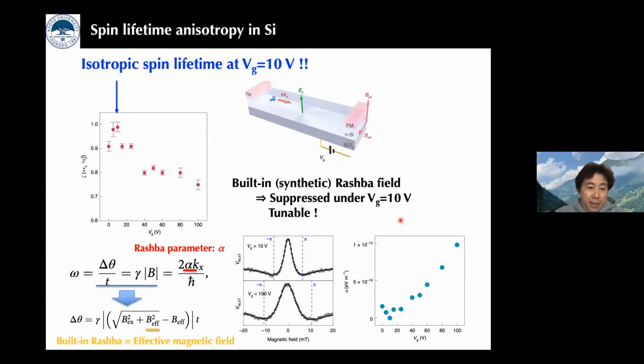This is the whole data set of the anisotropy factor as a function of gate voltage. As you see, the anisotropy factor becomes far from 1 under strong gate voltages, and the factor is also gate tunable. The other important issue is that spin lifetime is almost isotropic at a gate voltage of 10 volts. At 0 volt, the factor is 0.9, but at 10 volts, the factor is almost 1. This directly means that the built-in synthetic Rashba field exists at the interface between silicon and SiO2, and this is suppressed under the gate voltage of 10 volts, which means it is gate tunable.